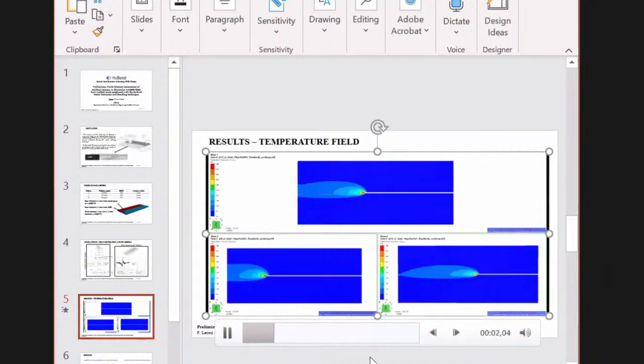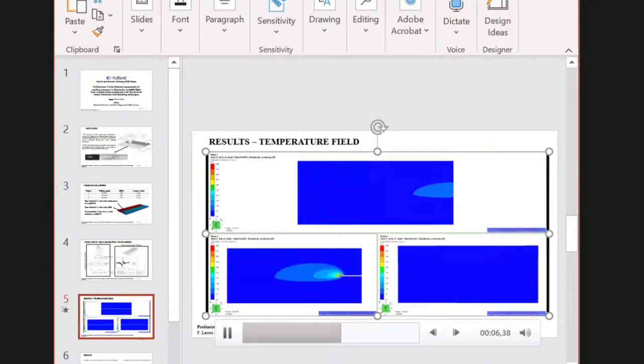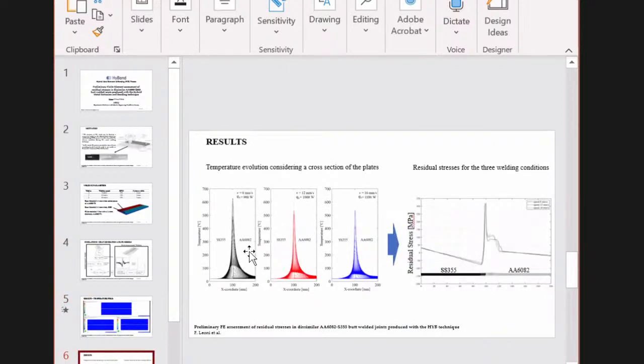So this is an example of how the temperature field changes with the welding speed. As you can see, at the lower velocity, the temperature field is wider, and this is observed also in these graphs, which are graphs of the temperature in the two materials, steel to the left and aluminum to the right, for the three conditions. And as you can see, the temperature drops as the welding speed increases, but this effect is lower than that which would be observed for fusion welding, where you can keep the power constant by adjusting the power of the electrode.